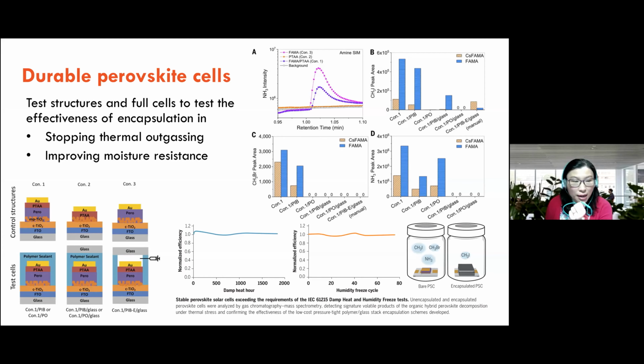And by blanket encapsulating the cell with glass, we were able to exceed the requirement of the IEC standard. The IEC standard is you have to maintain 95% of the initial efficiency after 1,000 hours. We were able to exceed that by 700 hours. Also, the IEC requirement is we have to be able to maintain the efficiency at 95% after 30 humidity-freeze cycles, but we're able to do 75.